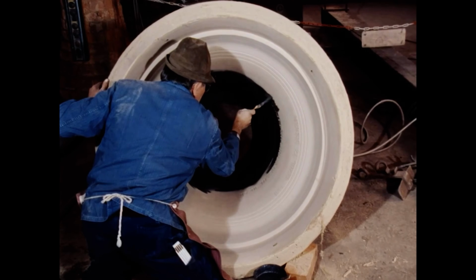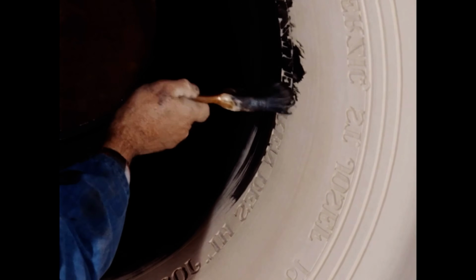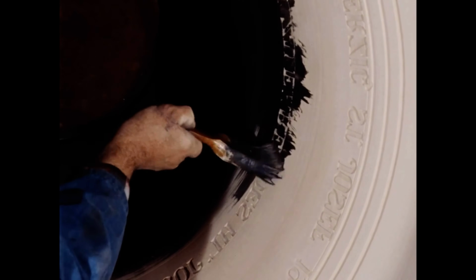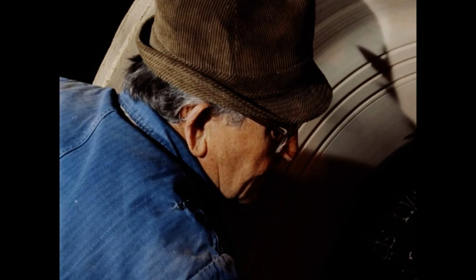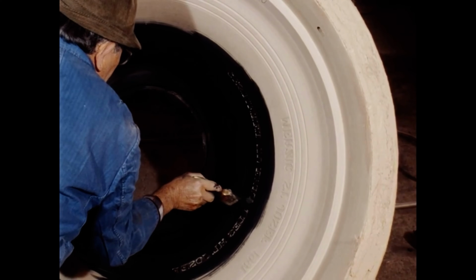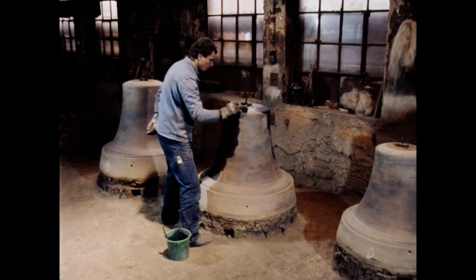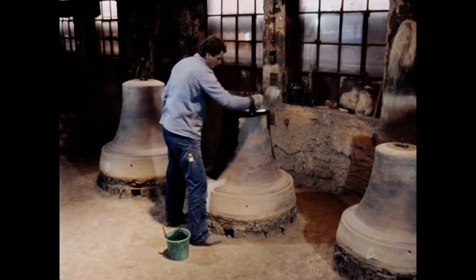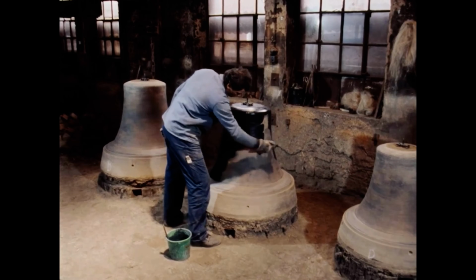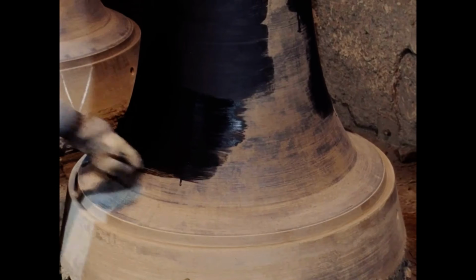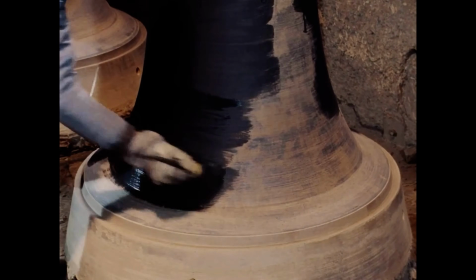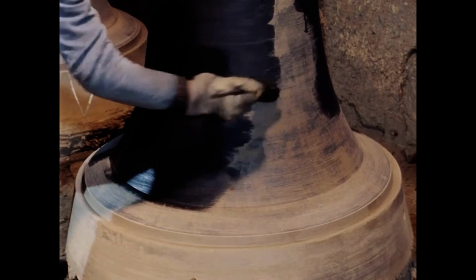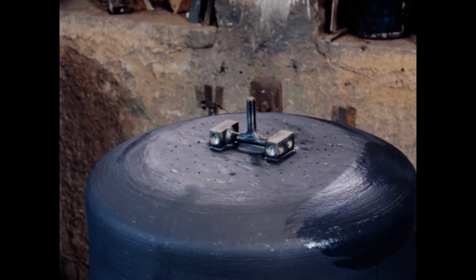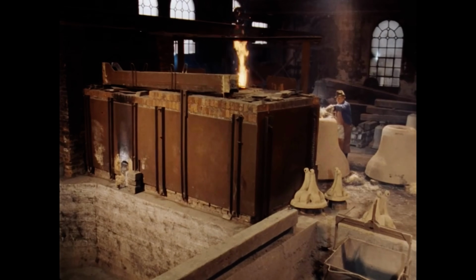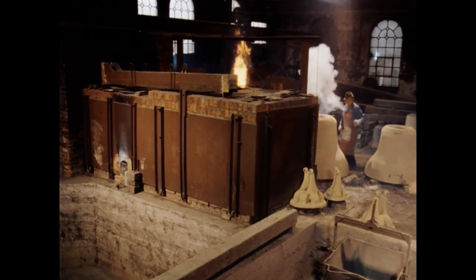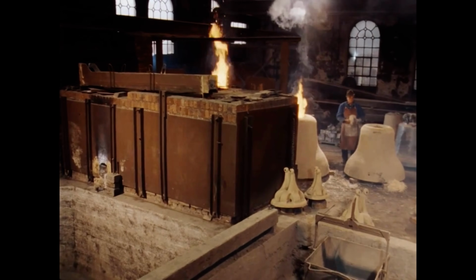He now coats the inside of the shell with graphite, paying particular attention to the letter impressions of the inscription. The bell core also receives a similar graphite coating. This is intended to prevent the cast metal from sticking. The first working day of the casting week ends with the flame curing of the shells, and the firing of the cores of all the bell molds. The graphite layers must dry quickly, and the molds should not be placed in the casting pit while cold.